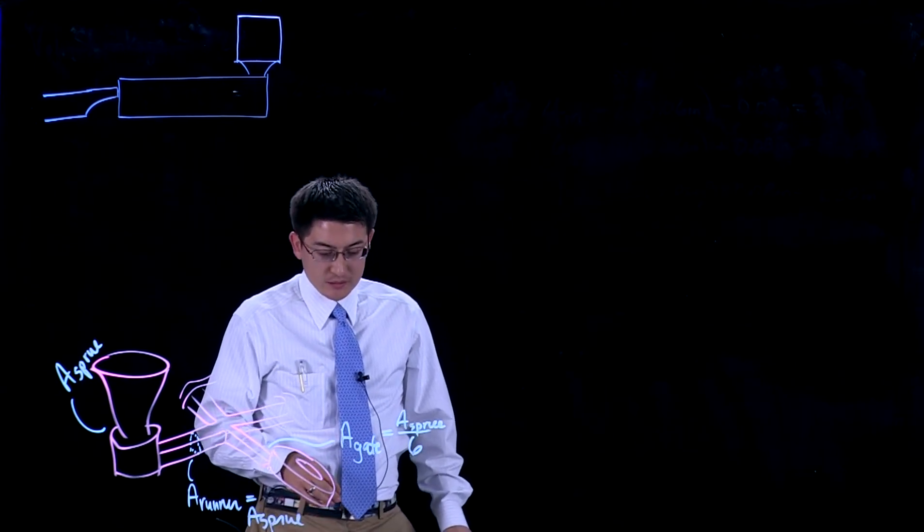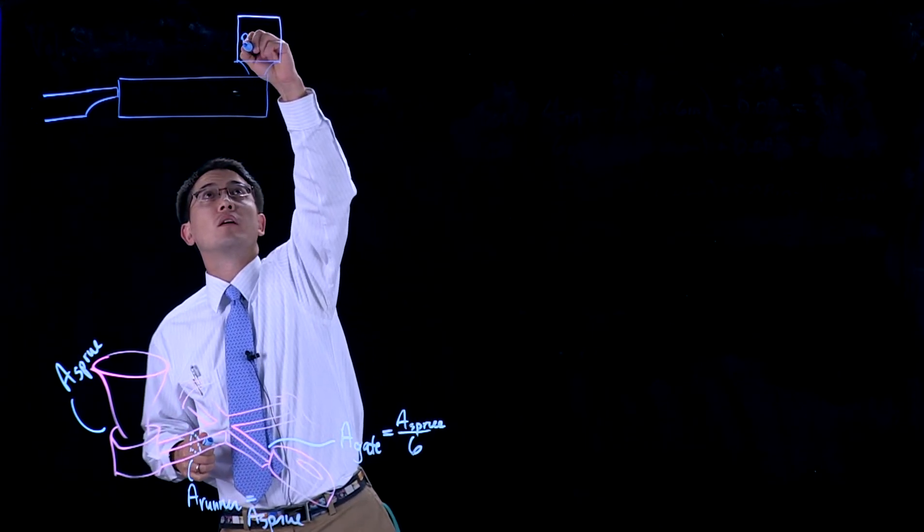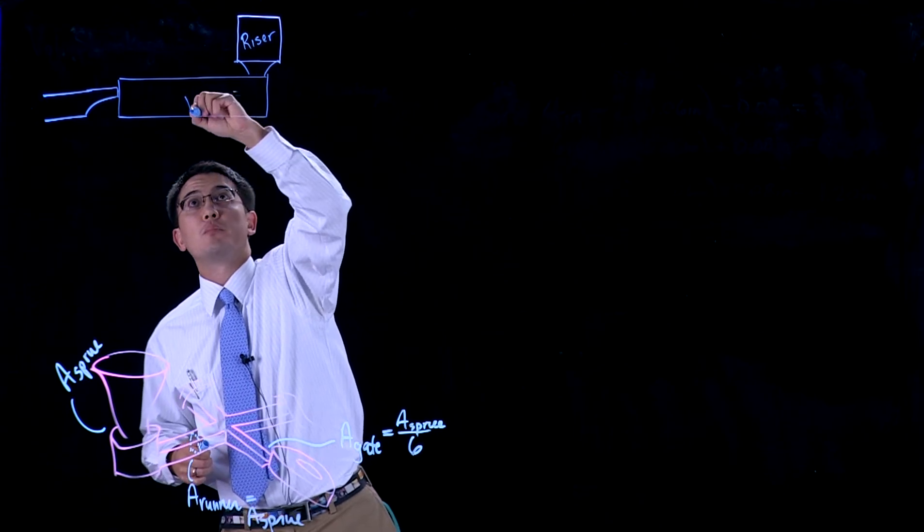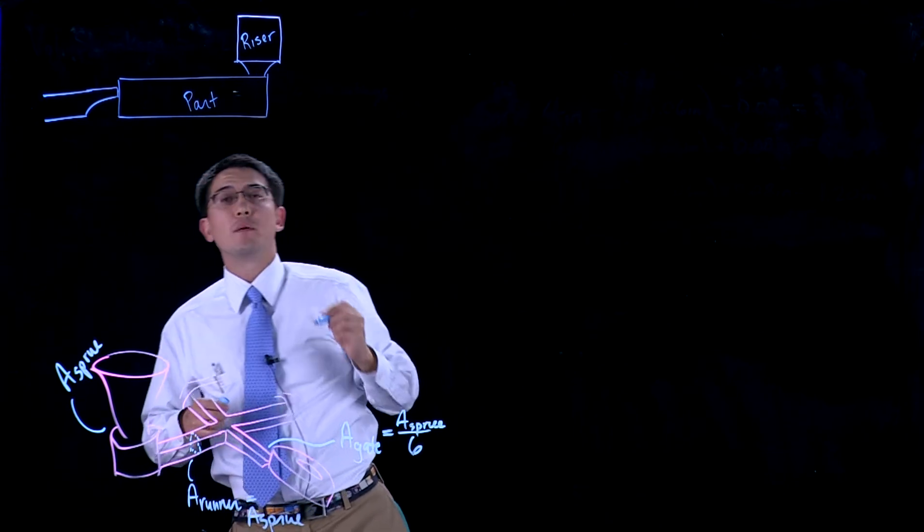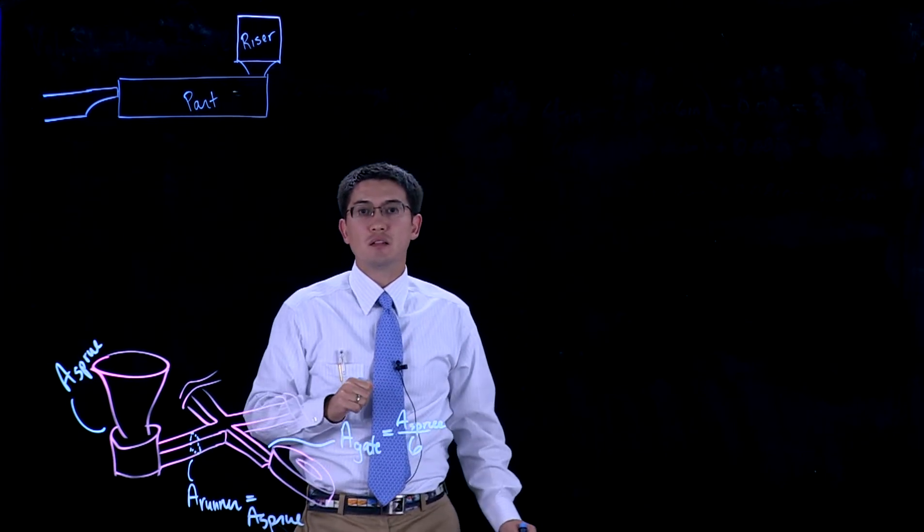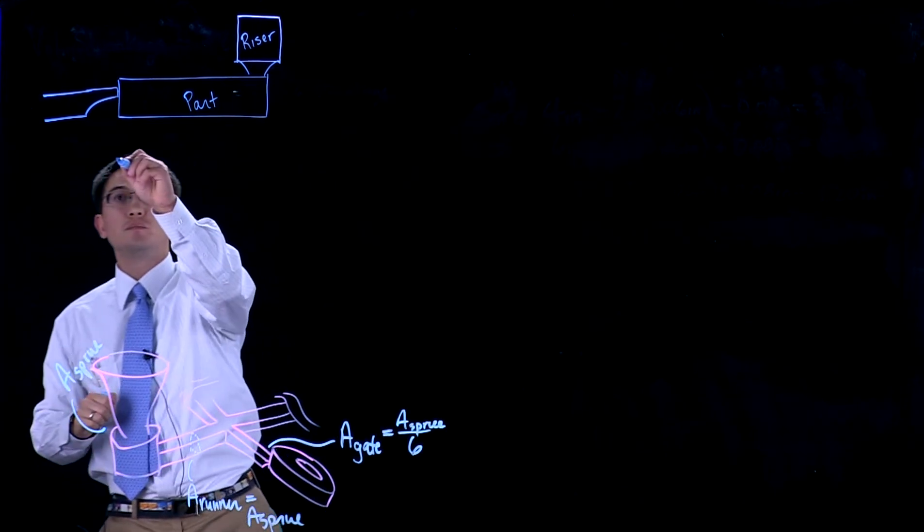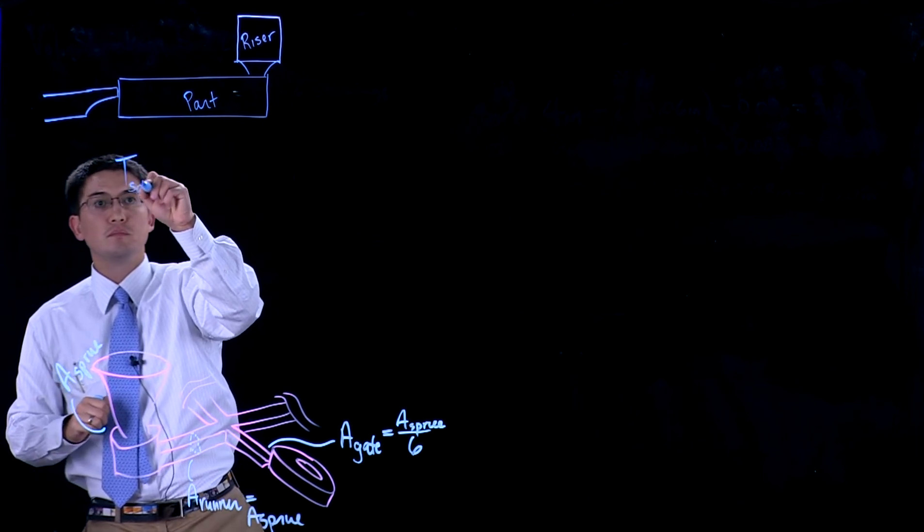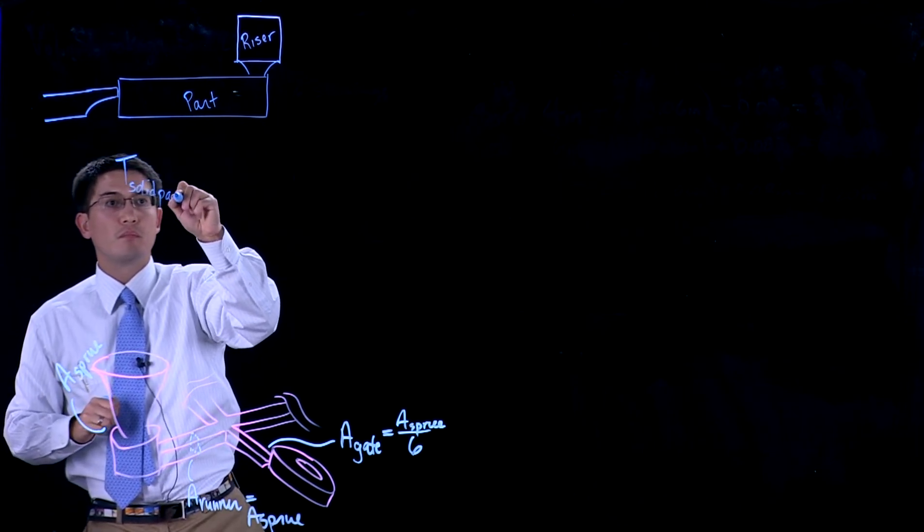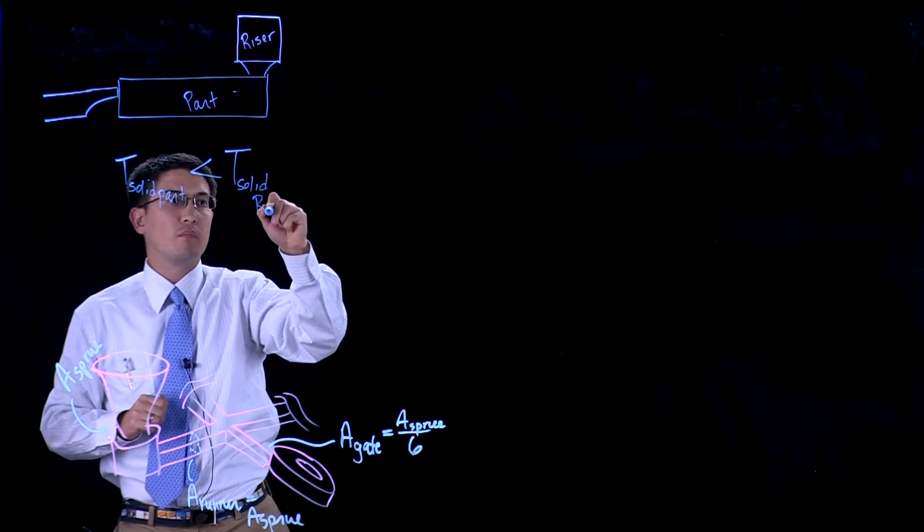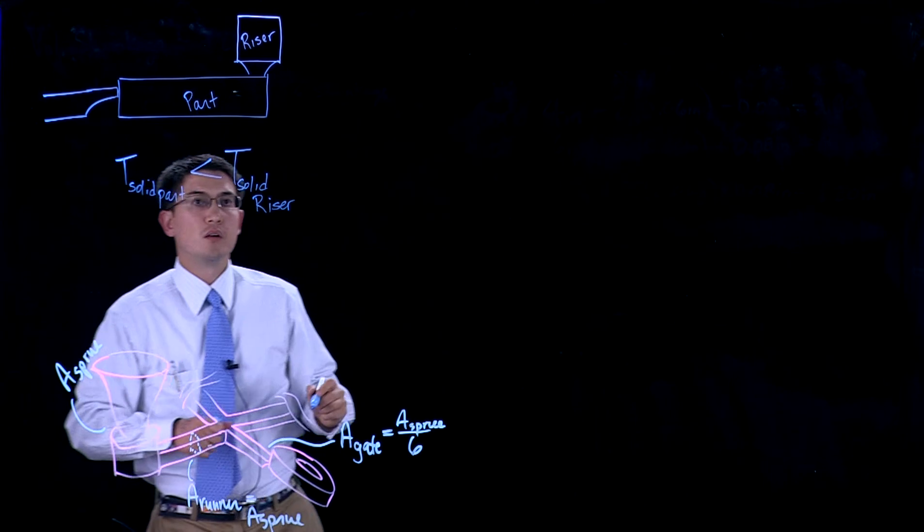Now we need to calculate and make sure that the solidification time of your riser. This is your riser, this is your part. You want to make sure that the solidification time of your part is less than the solidification time of your riser.